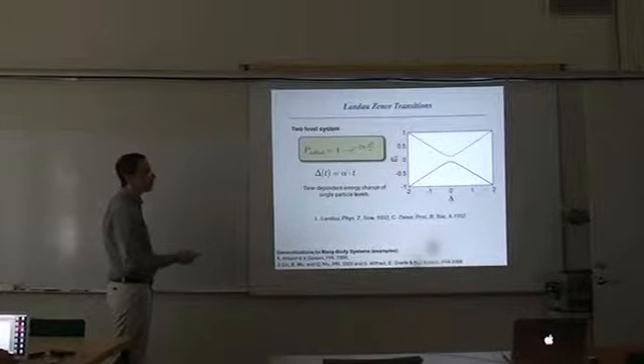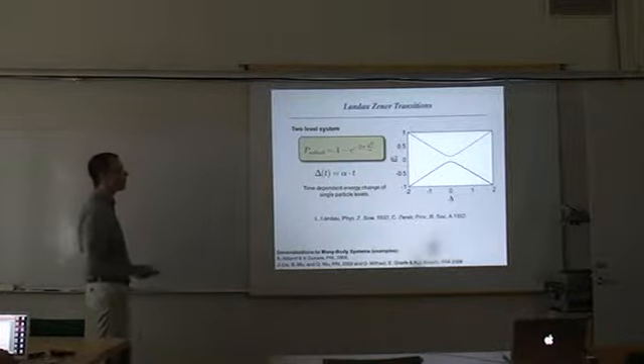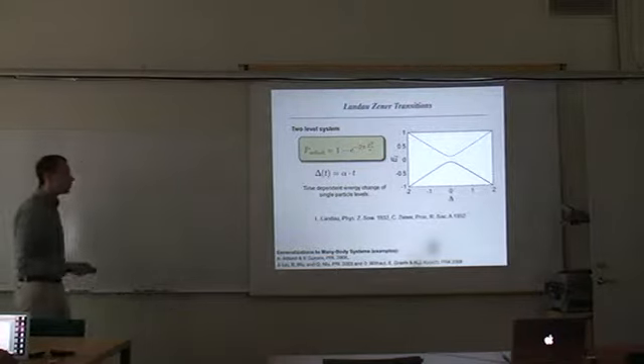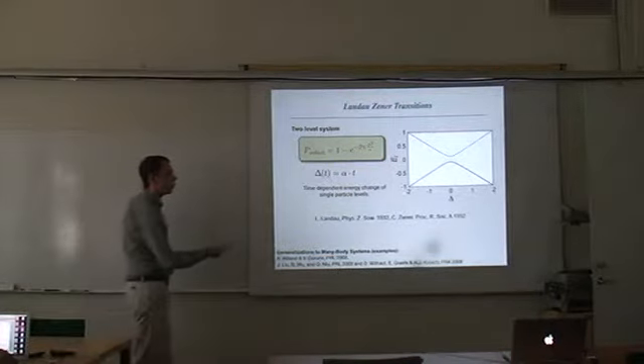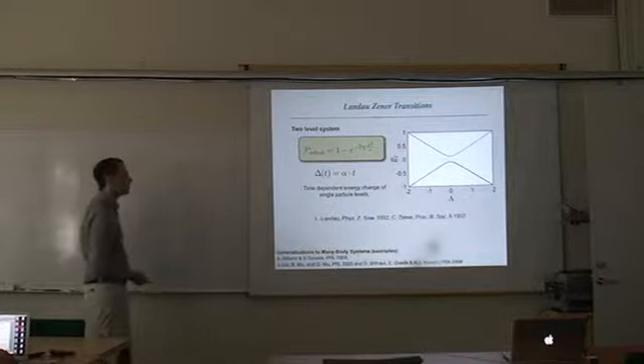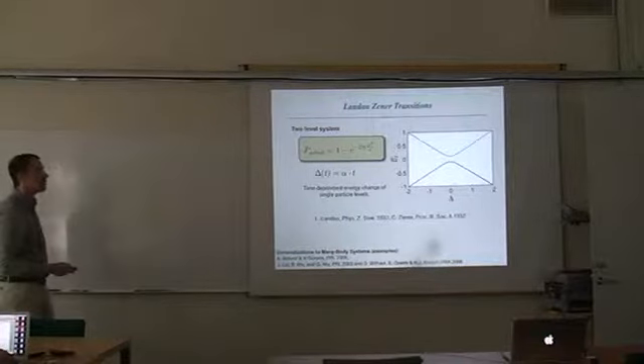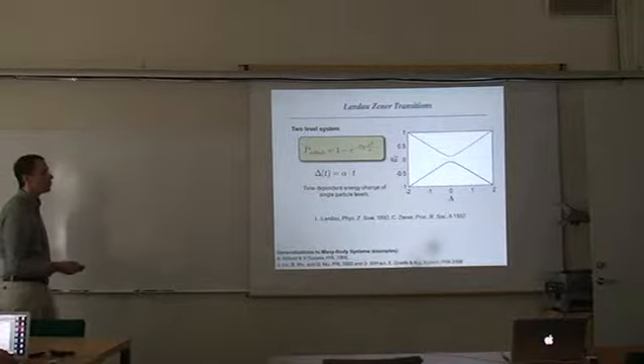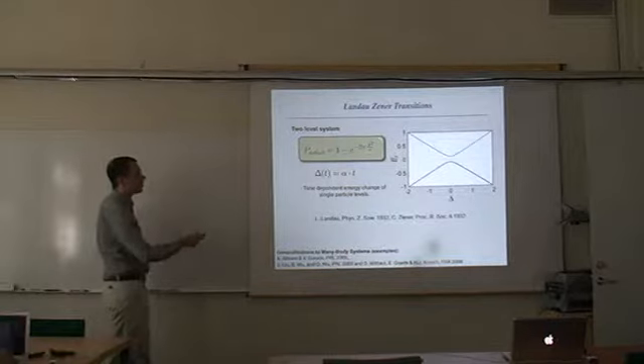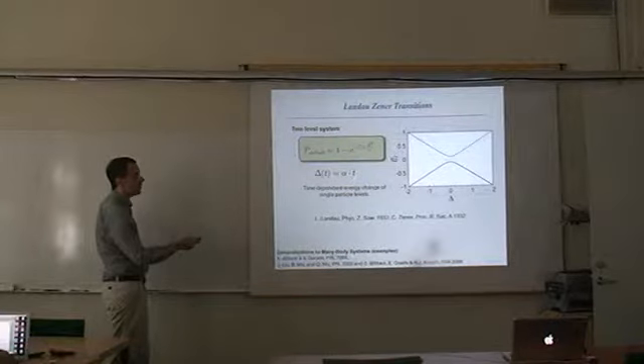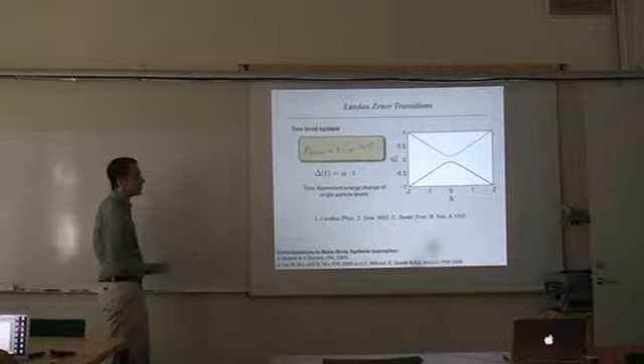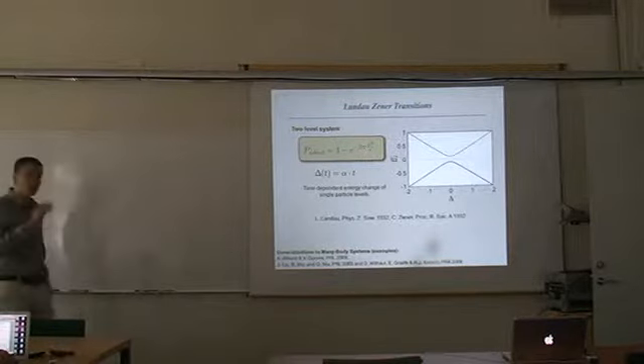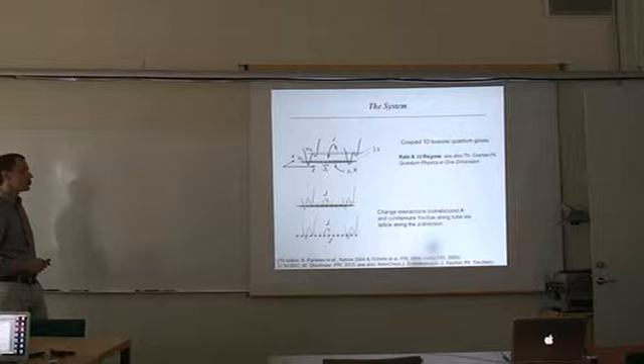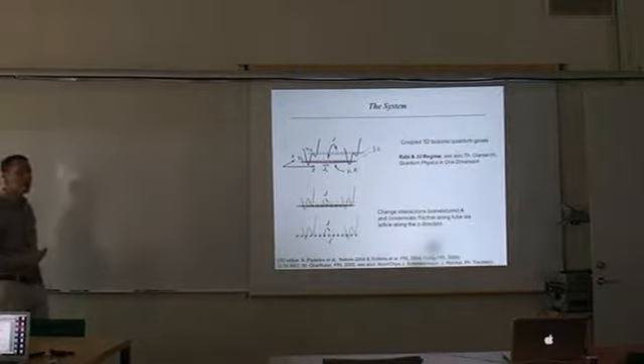If you have a coupling between the energy levels, then of course you get an avoided crossing. The Landau-Zener formula tells you, for example, the probability to stay on this curve, to be adiabatic on this curve. The parameter that characterizes the efficiency with which you stay adiabatic is given by the coupling strength squared divided by the ramp rate alpha in your system. That gives you the fidelity of staying on this adiabatic curve. So that's the two-level system. Now let's see what changes if you have a many-body system.